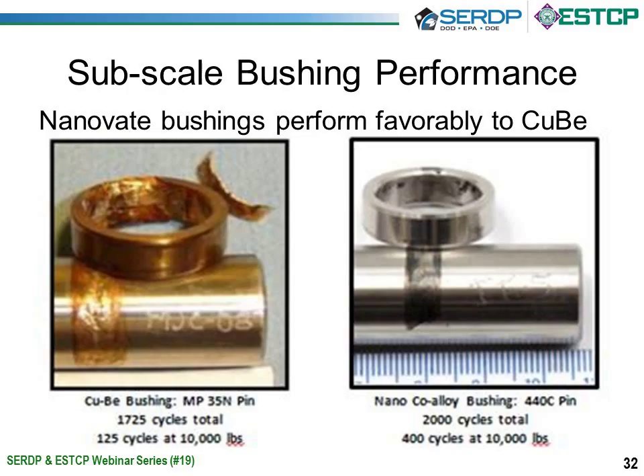Then the pin is rotated plus or minus 45 degrees for 100 cycles, after which the load is increased by 500 pounds. This continues up to a load of 10,000 pounds, after which it's finished off for 400 cycles at the maximum load.